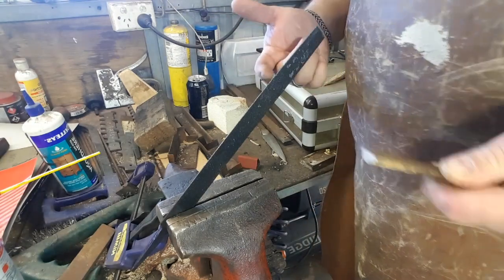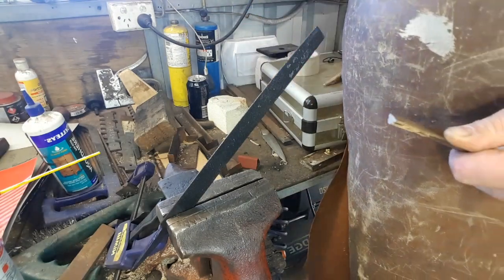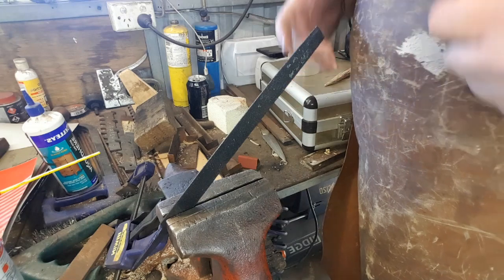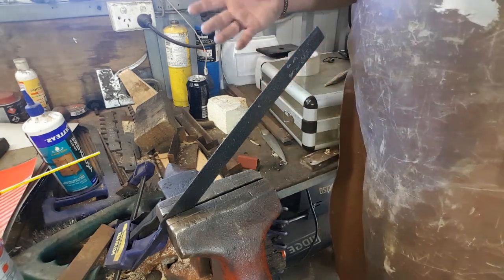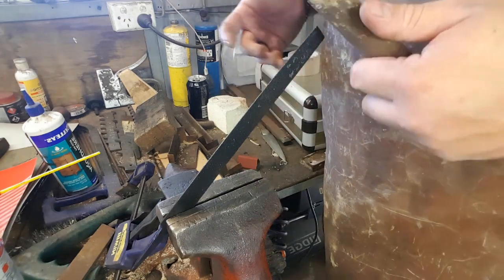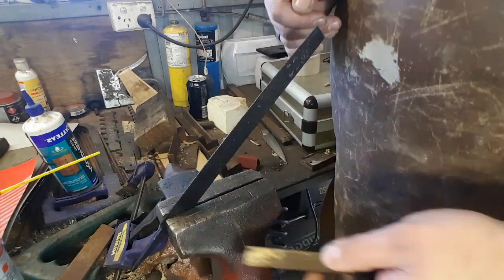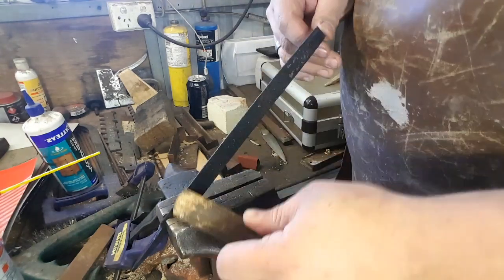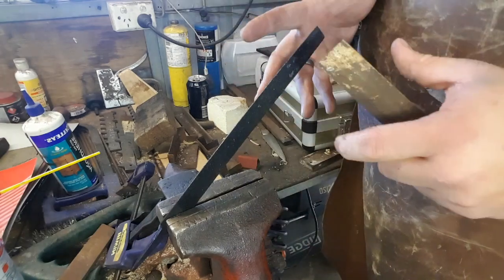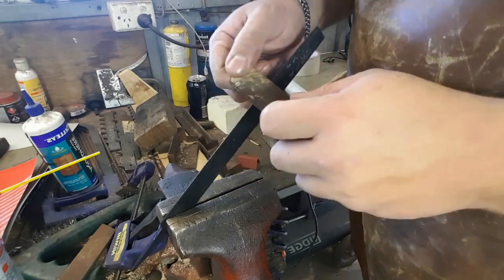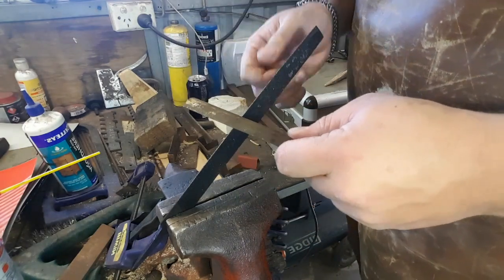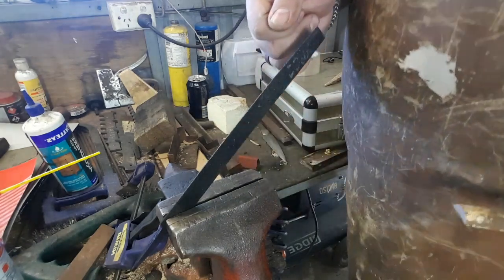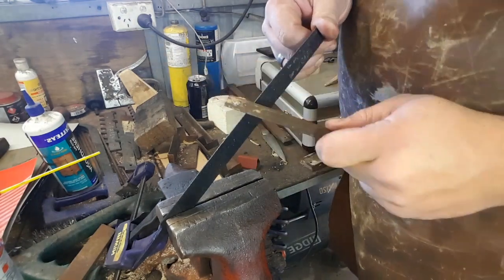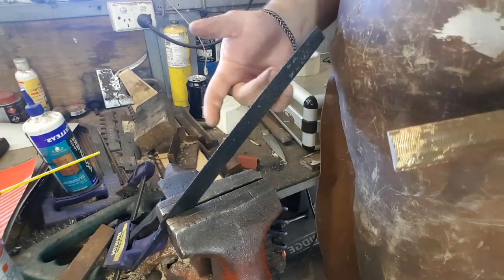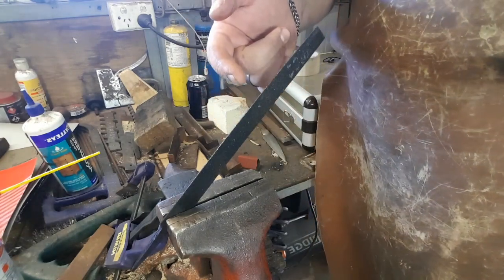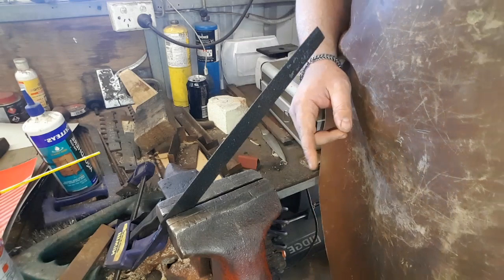And I've actually reheat treated blades that I thought I'd failed to heat treat, only to find out that it just had a layer of decarb, and I'd further decarburized the steel in the second heat treat. So make sure you go at it, get through that layer of decarb, especially on thin portions, and see if it escapes. If you can cut down with a corner of a file, if you can cut a notch in it, which I can't with this, then you obviously need to go back and reheat treat it.